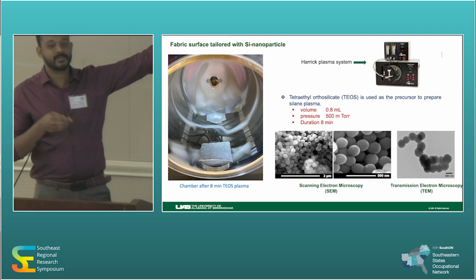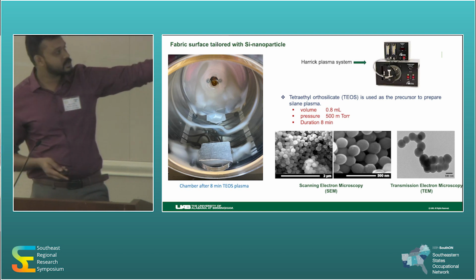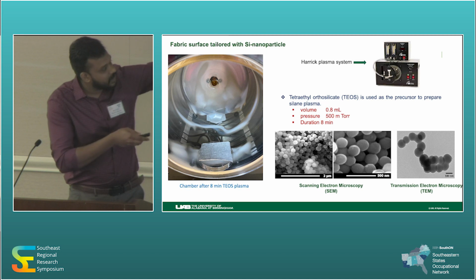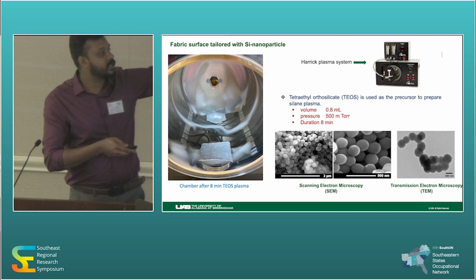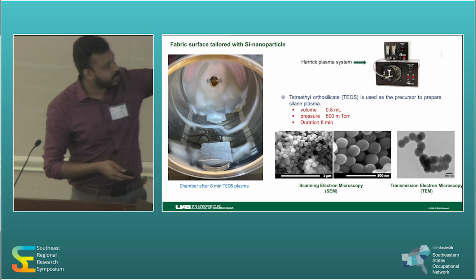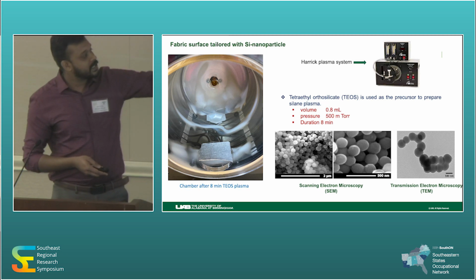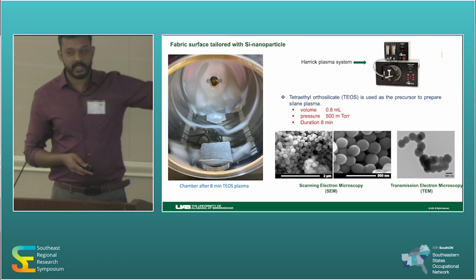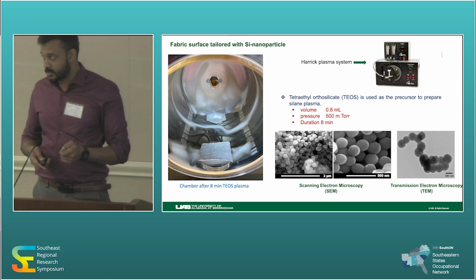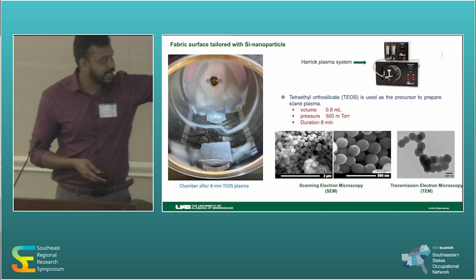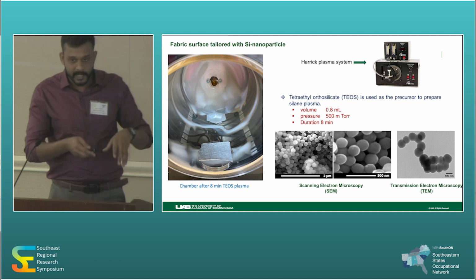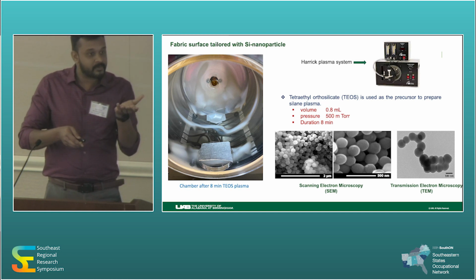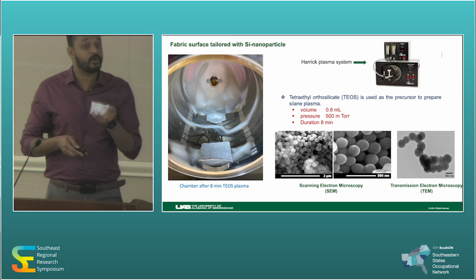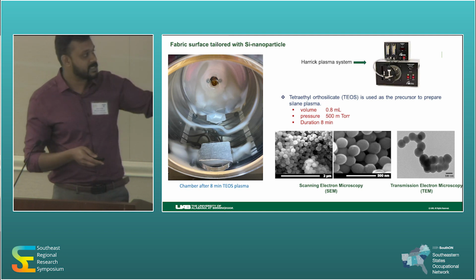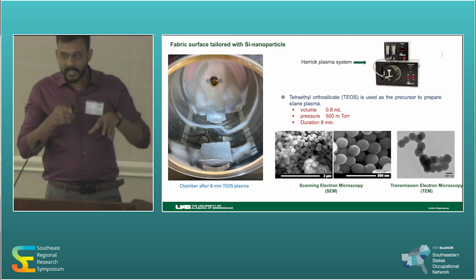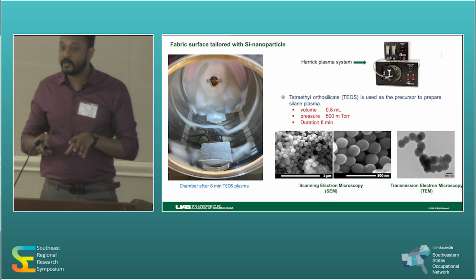Then the plasma inside is said to be uniform, but actually it is not. Basically, where the coils are located, there will be high deposition of plasma. The white particles we scraped and analyzed with SEM and TEM, and we realized the nanoparticles are produced. That means if you place a fabric like what's seen in the figure and perform plasma treatment, the fabric will get coated with silica nanoparticles effectively, because from SEM and TEM, we realized silica nanoparticles are forming inside the plasma chamber.